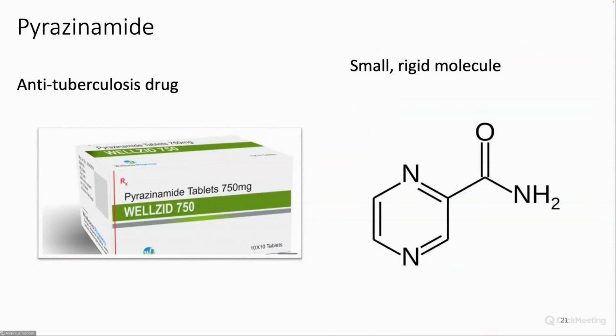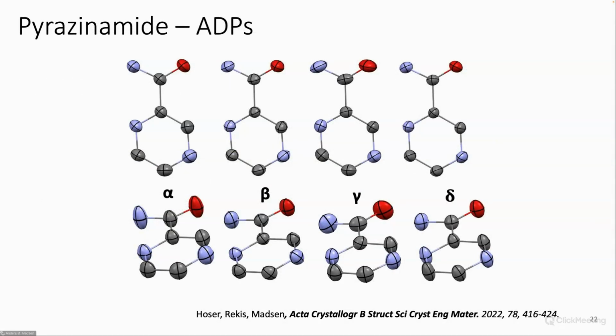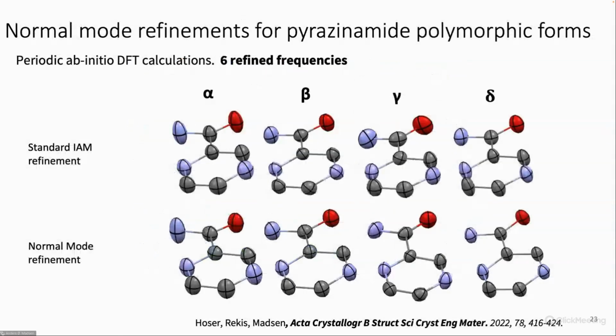Let's go back to pyrazinamide for a while. Now we have had a detour where we told about how to treat it. In pyrazinamide, we had these four different polymorphs, and we were thinking that perhaps there was a difference in the displacement parameters, and perhaps that would give rise to differences in entropy in the solid state. On the top row here, you see the experimental ADPs refined with a standard independent atom model, and down here the same ADPs, but this time derived based on this normal mode refinement. As you can see, there are not that big differences. There are some differences, but it seems reasonable that we have a reasonable model of the anisotropic displacement, or the Debye-Waller factors, of each of these atoms based on this normal mode refinement.